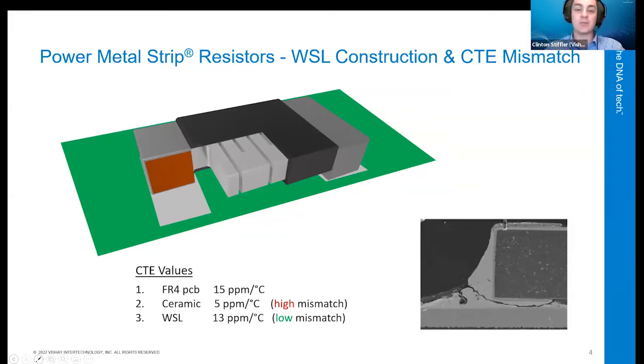In the case of the ceramic chip resistors, the rigid ceramic has a CTE of 5 parts per million per degree C, and this does not expand and contract at the same rate as the FR4 material at 15 parts per million per degree C, which applies a shear stress to the solder joint. Over time, the stress causes work hardening of the solder alloy, causing embrittlement, and then fatigue stress cracking, which you can see in the bottom right corner, which can lead to resistance value change in the connection or failure.